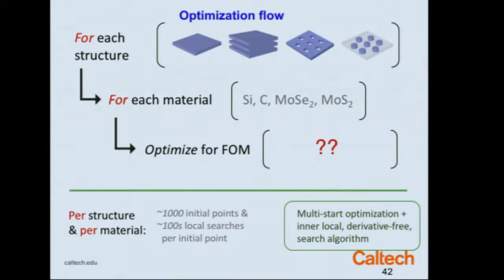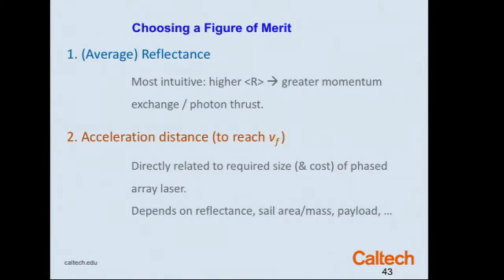So we started with thinking about what are the figures of merit, and we have many different points where we seeded the algorithm. And we decided there are a couple possible figures of merit. First would be just make the reflectance as high as possible. That seems fairly intuitively reasonable. So you have more momentum, and if the reflectance is very high, you could perhaps mitigate the absorption. Or you could use as your figure of merit to make the acceleration distance to reach the final velocity be as short as possible.